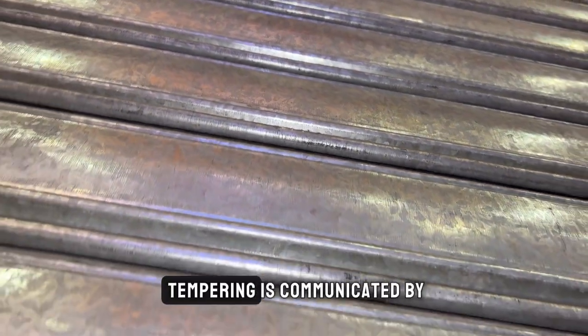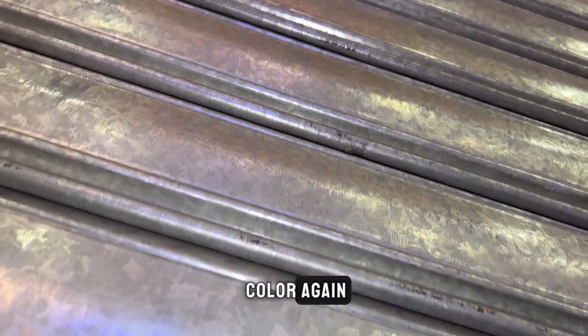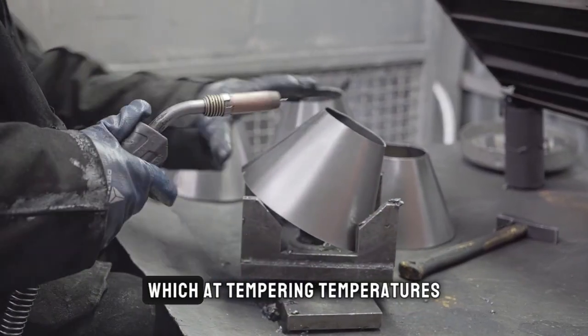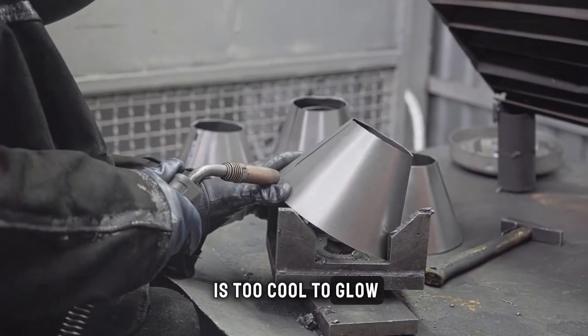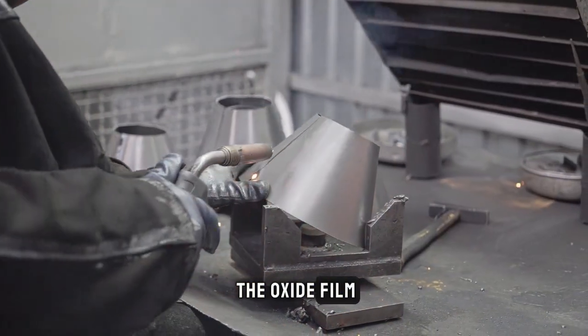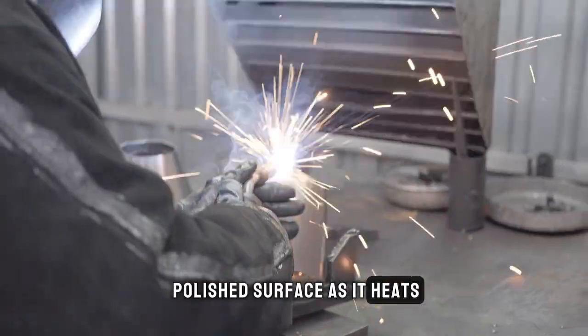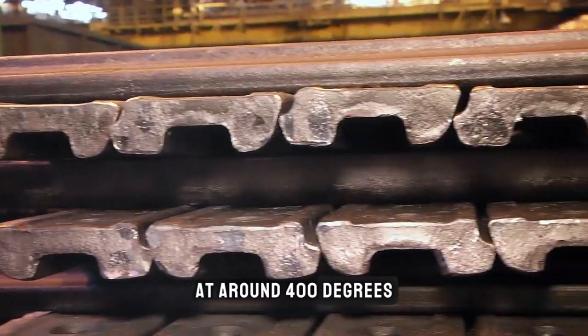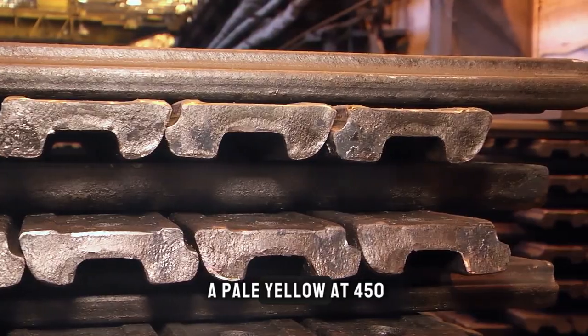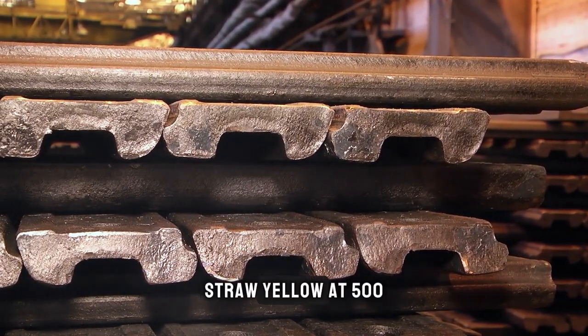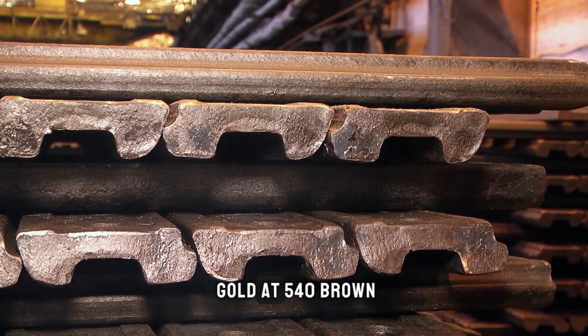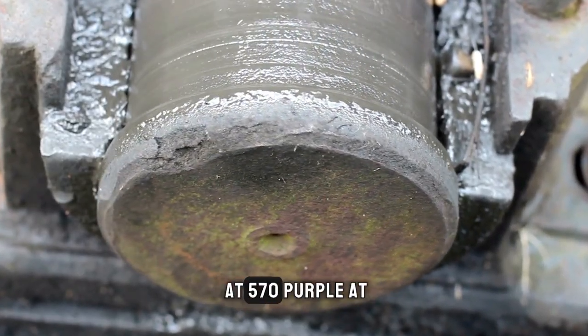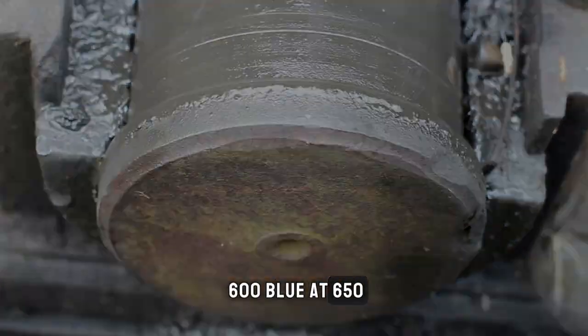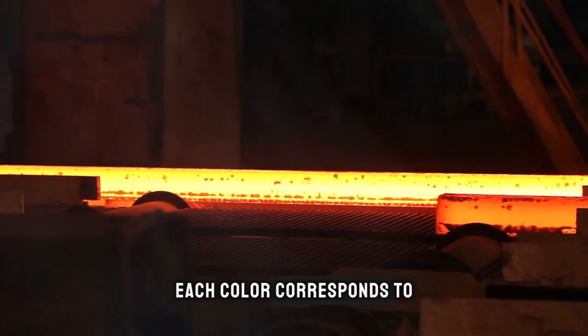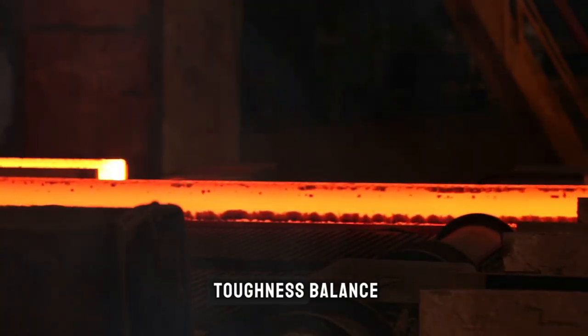The temperature for tempering is communicated by color again, not the color of the steel itself, which at tempering temperatures is too cool to glow, but the color of the oxide film that forms on the polished surface as it heats. At around 400 degrees, the oxide film is a pale yellow. At 450, straw yellow. At 500, gold. At 540, brown. At 570, purple. At 600, blue. At 650, gray. Each color corresponds to a specific hardness and toughness balance.